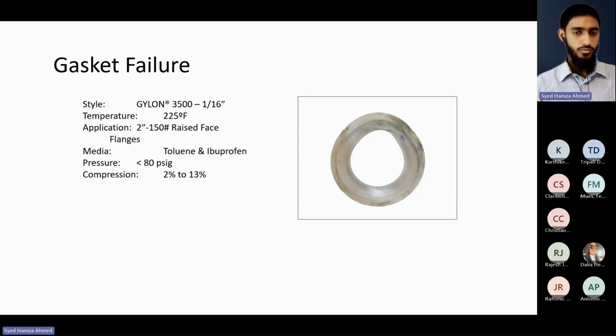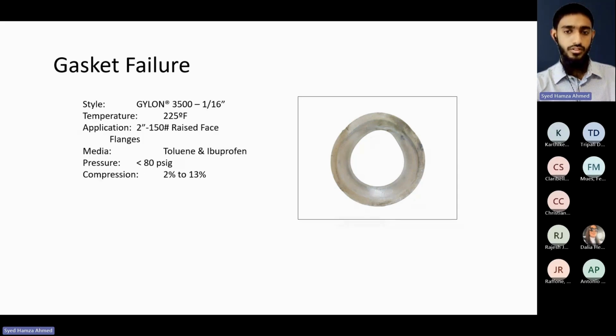However, we had seen a compression of 2% to 13% on the gasket, and this was due to the gasket not being compressed enough. There was not enough bolt load on the flanges, and this caused the media to basically deform the gasket in one direction and create itself a leak path. And here, this is where the gasket failed. So it is very important to have the correct torque values and to install the gasket with proper torque values.